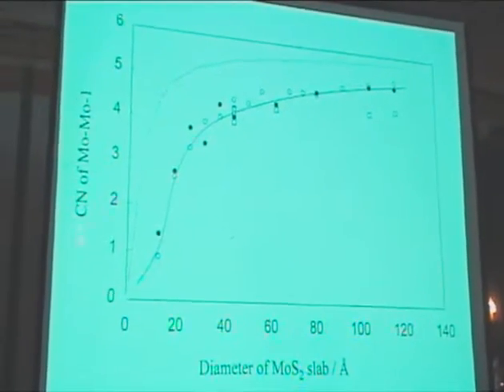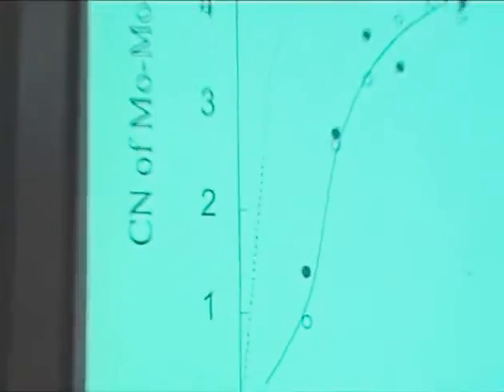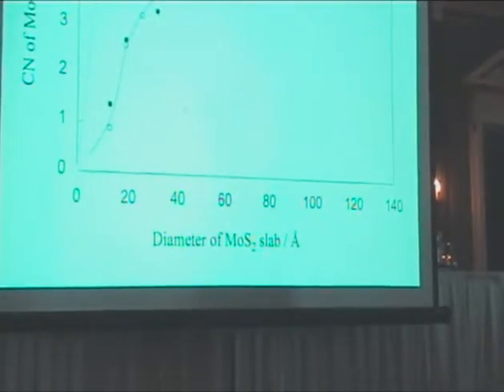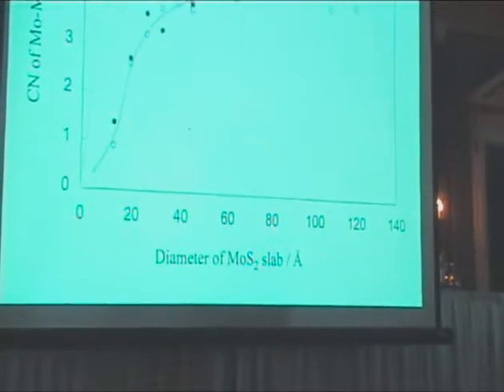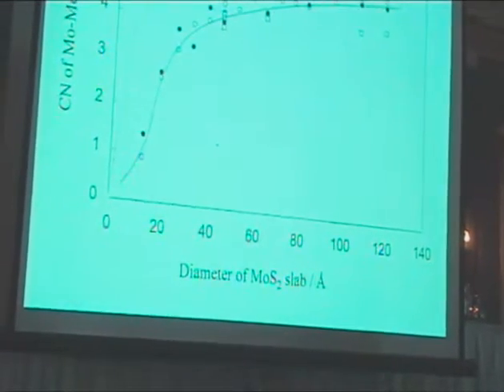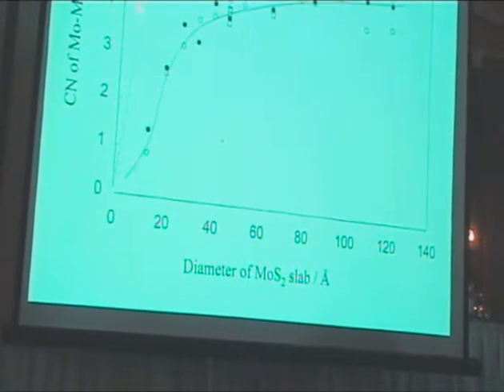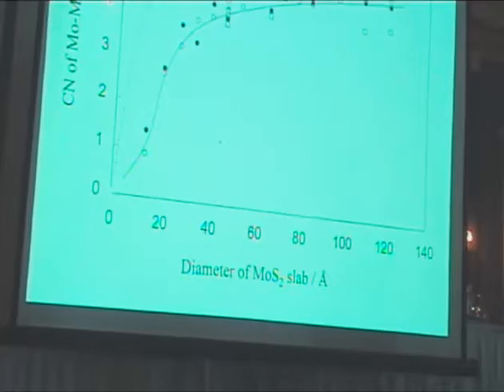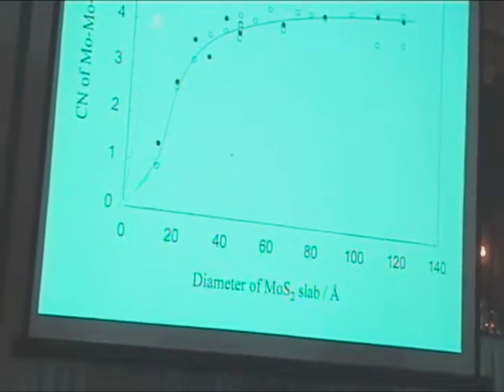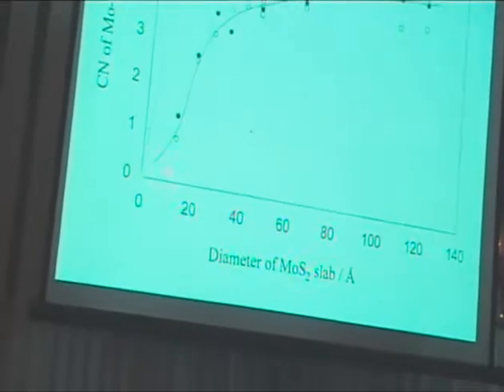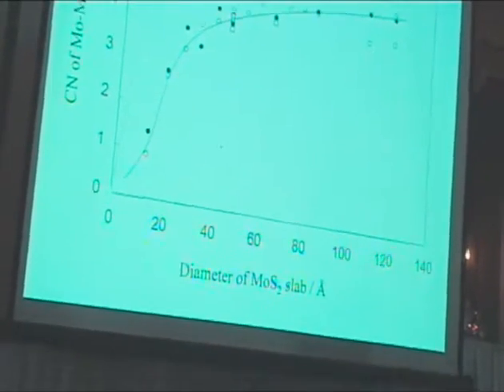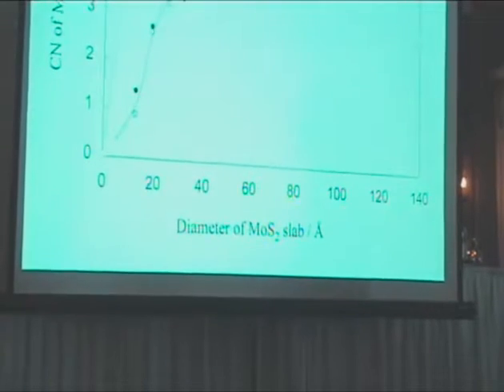The classic analysis method of EXAFS would give you this curve. This is the coordination number that you then can measure and analyze with the classic theory. And this would be the diameter of an MoS2 slab. And you see it goes up steeply and then it levels off. And 6 is the maximum, because in the plane of the molybdenum there are only 6 molybdenum neighbors. So if we would see a coordination number of 4 experimentally, this is what we decided originally. Okay, it must be here, so I go down. So my particle is only 10 angstrom in diameter, so I'm looking at very small particles. But I told you, TEM was seeing big ones.